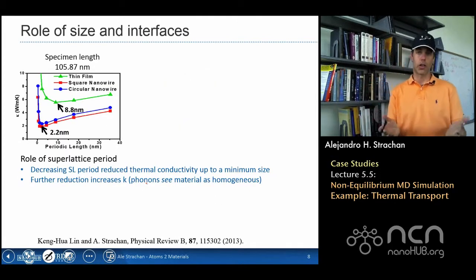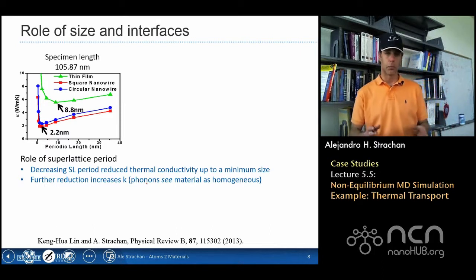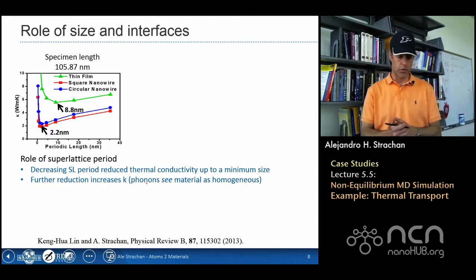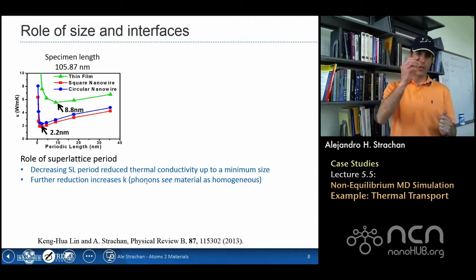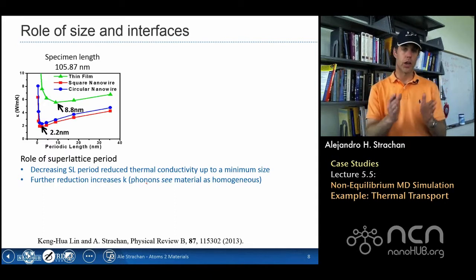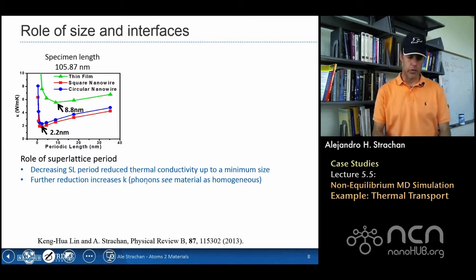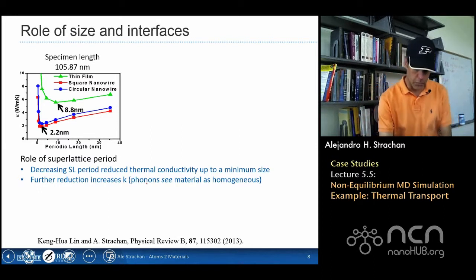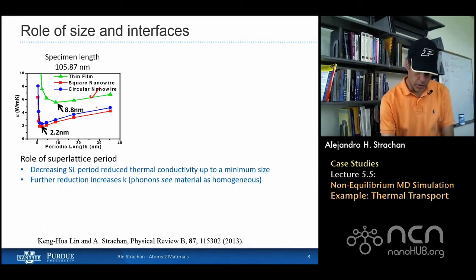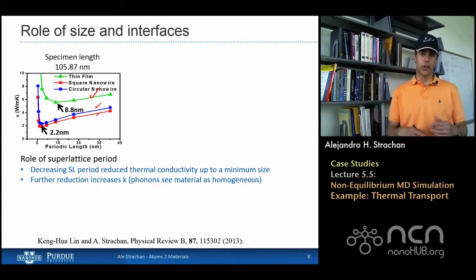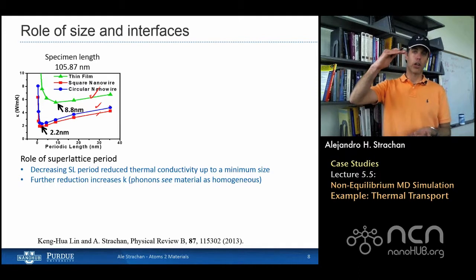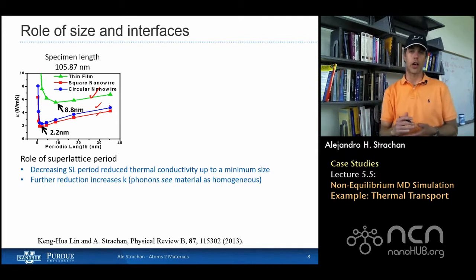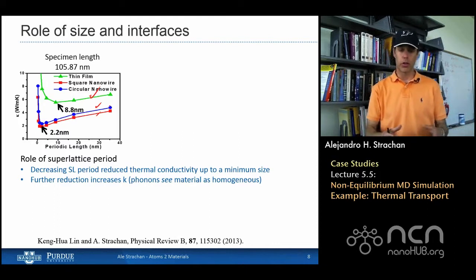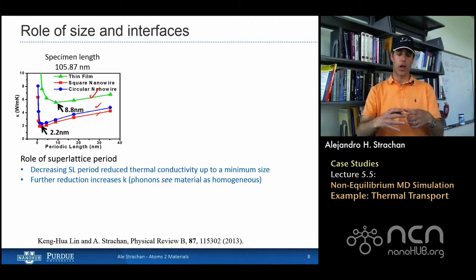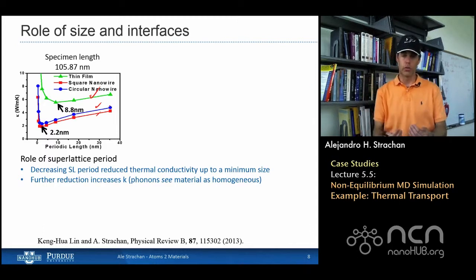Now, the interesting results that I want to discuss with you are the following. What I'm showing here in the plot on the top left is the thermal conductivity, kappa, as a function of the superlattice periodic length, okay, for the three systems. The thin film is in green, up here, and then the two nanowires. What you see is a couple of interesting things. The thermal conductivity of the thin film is higher than that of the nanowires. That's very easy to understand. The wires are very small, a few nanometers in diameter, so there's a huge surface scattering in these wires, and that reduces the thermal conductivity.